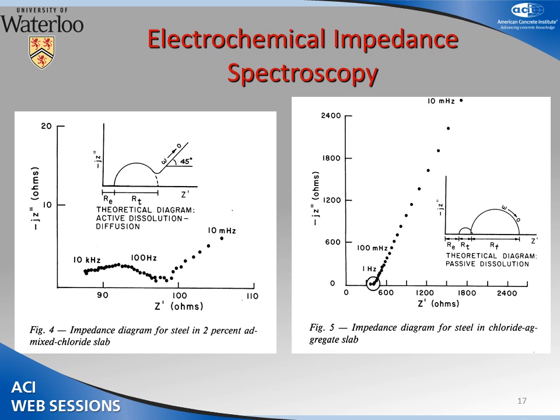He was also one of the first. At this time, there were probably about three investigators around the world using EIS, electrochemical impedance spectroscopy, to study corrosion of steel in concrete. And just to give you an example, this is the one with admixed chlorides. This is the Nyquist plot for admixed chlorides, and you can see there's not a large diffusion component, which is this one here, because the chlorides are available in the solution having been admixed. When the chlorides were present in the aggregate, as the contaminated aggregate, there's a much, much greater diffusion component that contributes to the threshold value.